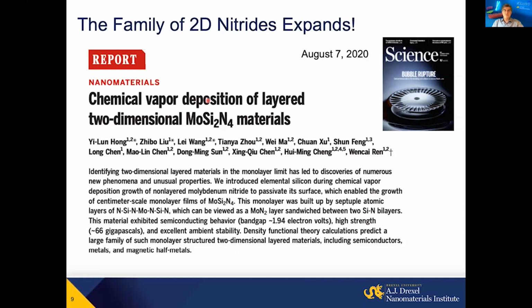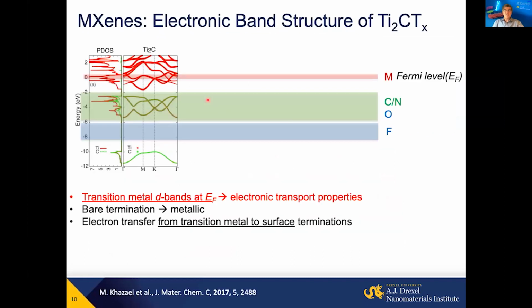So it's truly exciting because development of technology has been really driven by availability of new materials. Whenever we have new materials, we can do something new which could not be done previously. But of course, the key point is not just to make new materials. We have already quite a few, but to make materials with different properties from those available today, for example, metallic structures. Second, also learning how to precisely control those properties through structure, composition, and processing here. So what you see here is the density of states of titanium 2 carbon MXene with no surface termination, and you see high density of states at the Fermi level.